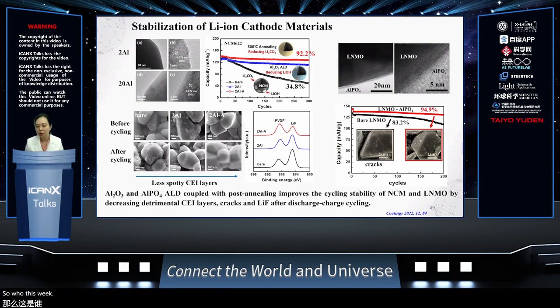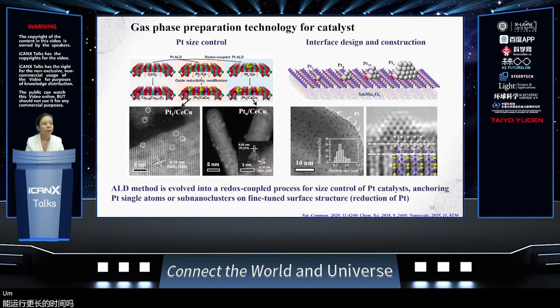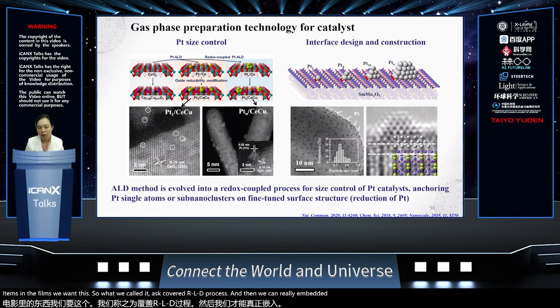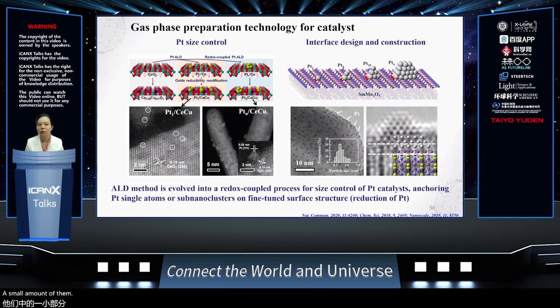So for this, we definitely found that with proper coating of the surfaces, with just a few angstroms, it helps to stabilize the materials and lets them run for a longer time. This also shows how we can use these processes to keep Pt as small single atoms in the films. We run this through what we call the redox coupled ALD process, and then we can really embed a small amount of the materials inside of the layers.